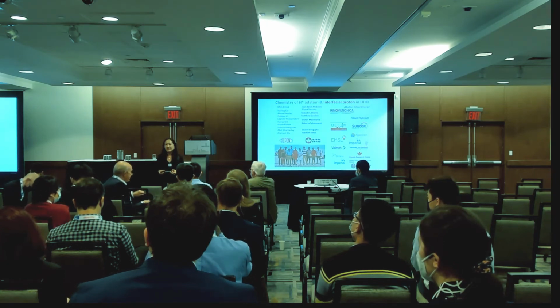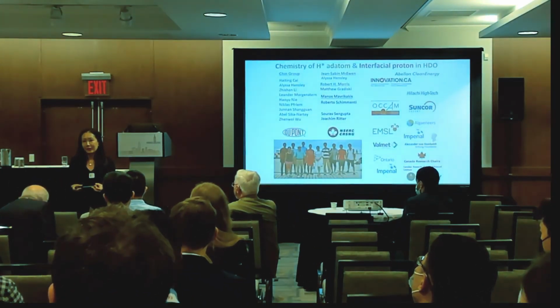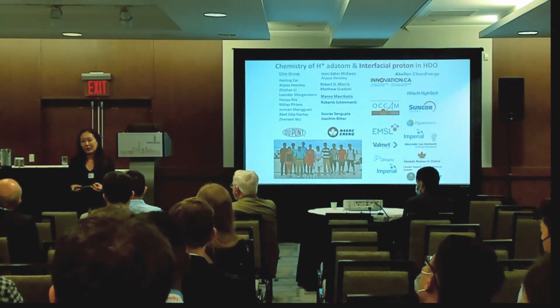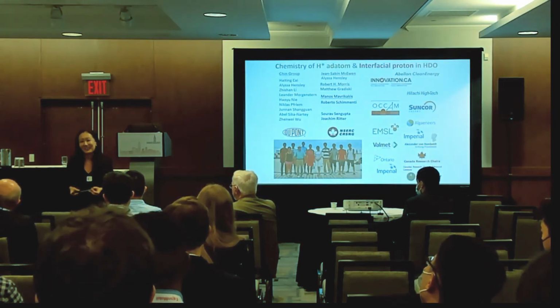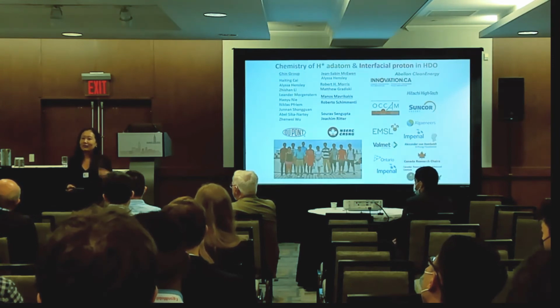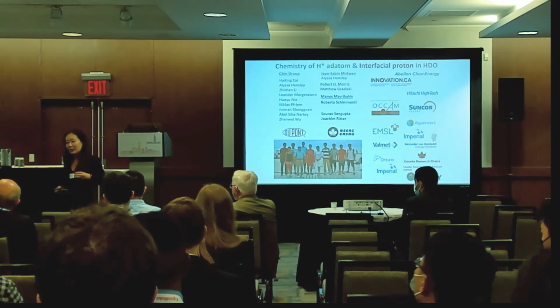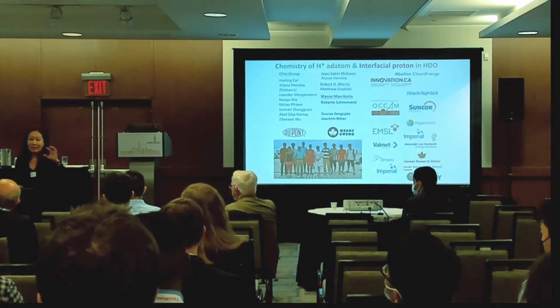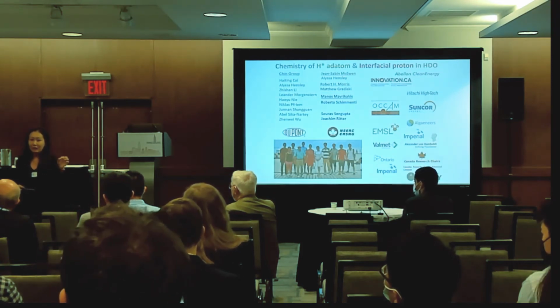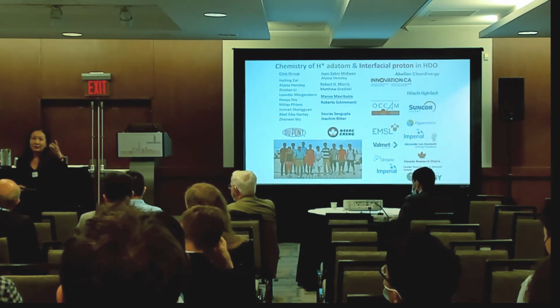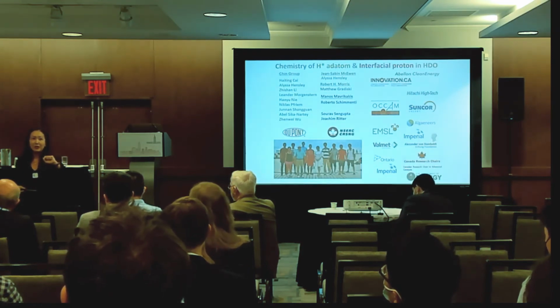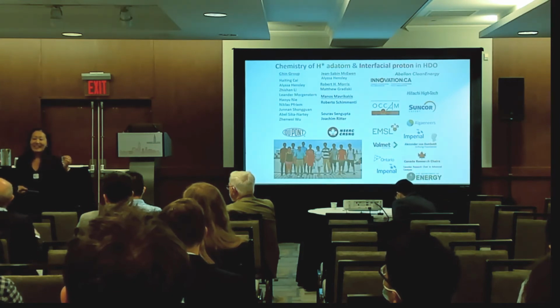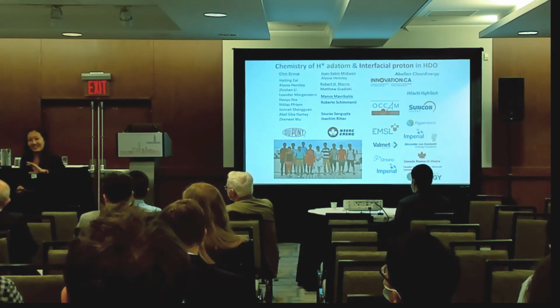I see. It depends on when we change the pH. That depends on how you change the pH, right? If you provide different ions, then we need to deal with non-ideal chemistry, and we need to account for the presence of the different ions. For example, a while ago we changed it by doping with some sodium, for example sodium acetate. And we need to be very careful about this because the acetate would adsorb on the surface.